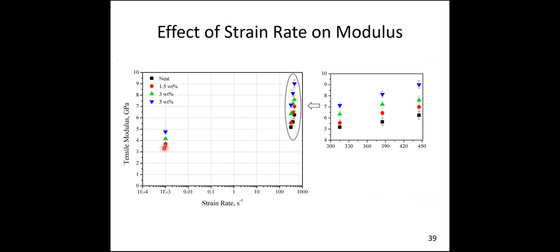Again, here I have shown the effect of strain rate on tensile modulus for different samples. The black shows the neat, and the red, green, and blue show the clay samples. When I keep on increasing the strain rate, my properties keep on increasing. We could also see the addition of clay leads to improvement in the tensile modulus. For example, the black is the epoxy. We got 5 gigapascal as a tensile modulus, whereas this blue is the 5% clay. With the addition of clay, we could get an improvement from 5 to 7 gigapascal. So this is what I wanted to convey to this forum.